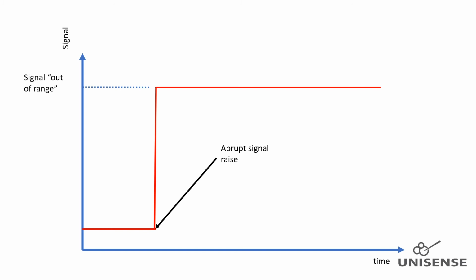I now turn to troubleshooting nitrous oxide microsensors which do not exhibit normal performance. A broken sensor will in water give a very high signal, typically out of range, as the polarized working electrode is directly exposed to the sample. So if the tip breaks during measurements, a sharp signal rise will occur to the out of range signal.